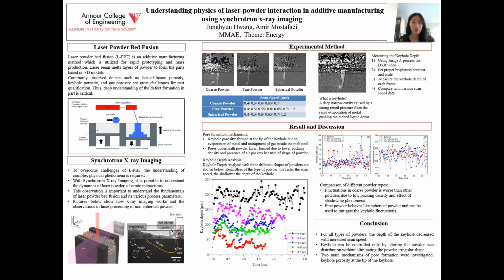Keyhole porosity is formed at the tip of the keyhole because of the evaporation of metal and gas entrapment inside the melt pool. Also, there were pores made underneath the powder layer, which were formed because of the low packing density and air pockets.